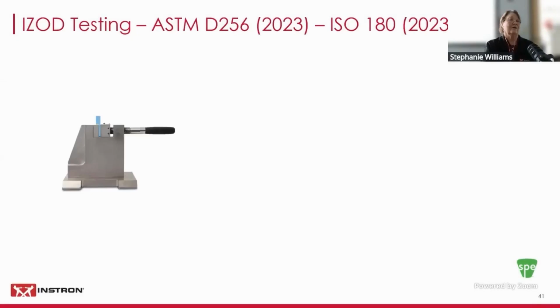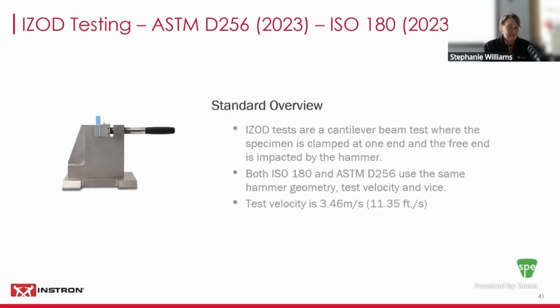So now let's look at Izod. Izod is actually the most commonly run pendulum test in the US. ASTM and ISO both each have a version of it, D256 for ASTM, ISO 180. Both standards were revised in 2023. It's a cantilever test, meaning that the sample is perpendicular to the impact plane. The notch faces the hammer, so it's facing into the impact plane. We center on the notch, the same as we did with the Charpy test.